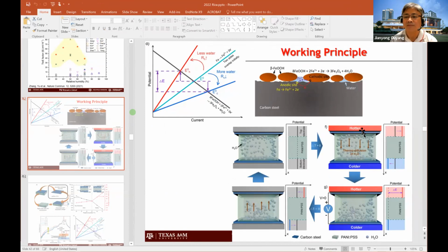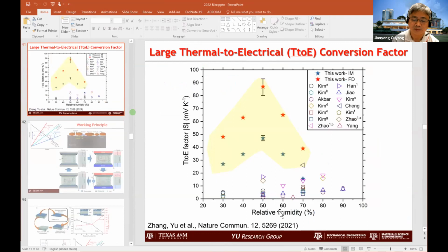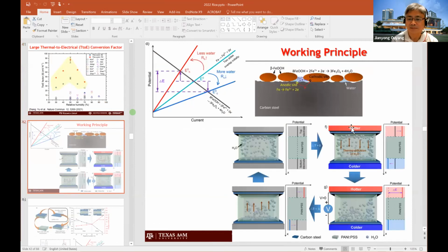It is actually a hydroelectrochemical sort of effect. When we have one side hotter and the other colder, the water is migrating, and it is drier on the hotter side than on the colder side. So more water is getting into the colder side. That is one of the reasons why this becomes maximized whenever we have a relative humidity of, say, 50%. If every pore in the electrode is filled completely by water, then there is no difference between hotter and colder side. We just need to have it sort of half filled. Then when water is pushed inside the colder side and escapes from the hotter, the difference is maximized.